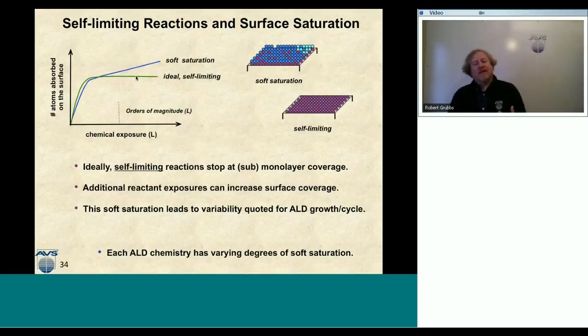But you're going to notice in the literature that some people quote certain angstroms per cycle that are different. I know that titanium oxide is one of them. And so what we can have there is a softer saturation. And that's that we come up on the curve with the number of atoms absorbed on the surface. But as we increase the chemical exposure, possibly maybe if we add orders and orders of magnitude more chemical on the surface, we'll actually start to get more atoms absorbed onto the surface. And this is called a soft saturation.